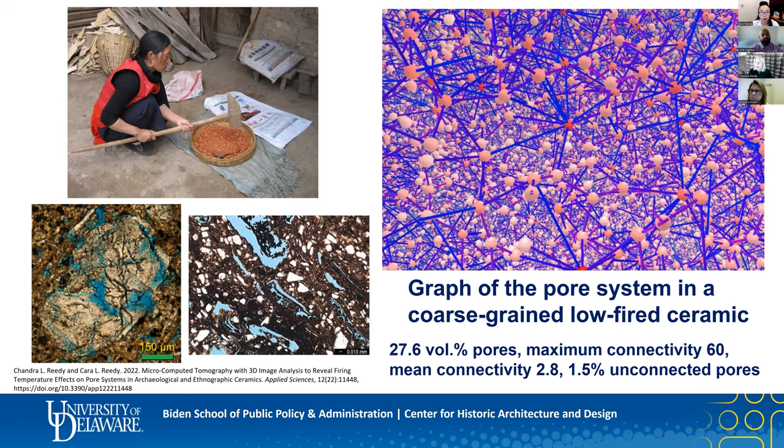When clays are coarsely ground and coarsely sieved, as on the upper left, with coarse additives and then fired at relatively low temperatures, the sherds tend to have high pore connectivity values. And this can be both visualized and quantified in Dragonfly by viewing the segmented pore systems as graph models of the system with spheres representing the pores and lines between them, the pore connections, as we see on the right here.